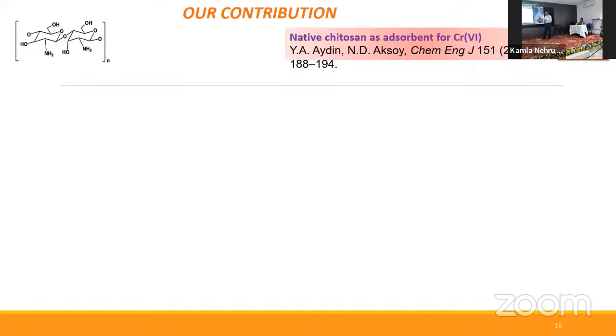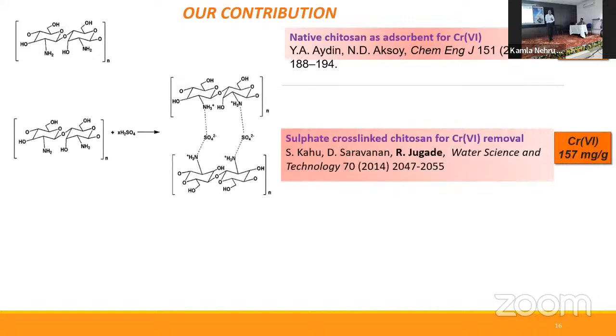What we did, we started our work with chitosan, and it was reported in literature long back in 2009 that native chitosan can be used as an adsorbent for chromium with an adsorption capacity of 22 milligrams per gram. What we did is we just carried out a simple cross-linking with sulfuric acid, and we found that the cross-linked chitosan, which was formed by sulfuric acid cross-linking, improved the chromium adsorption capacity to about 157 milligrams per gram. So from 22, we improved it to 157 milligrams per gram.